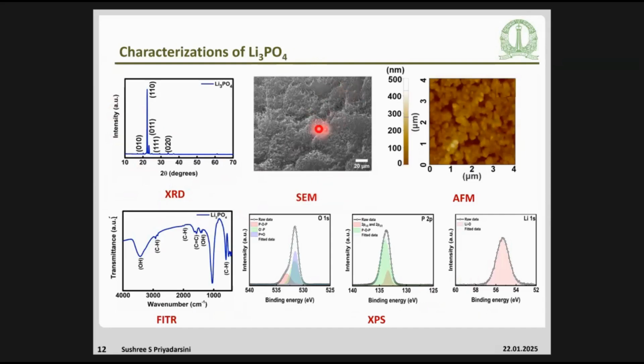And when you see that in SEM, it looks like a very homogeneous structure. But when you see it in AFM, you see that these are particle structures. And then I will tell you next why these particle structures are important. So now next is FTIR, to understand whether it can absorb water at room temperature, where the relative humidity was 45%. There we see that the OH group is already there in the structure. So also you can find CH, C double bond C and OH groups.